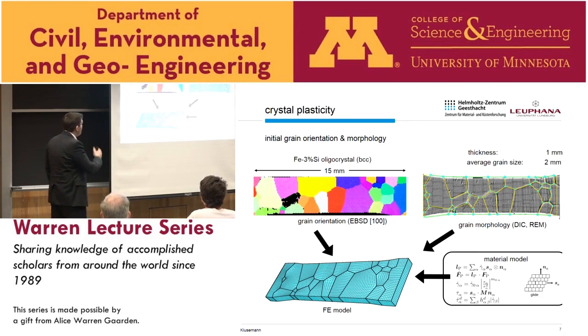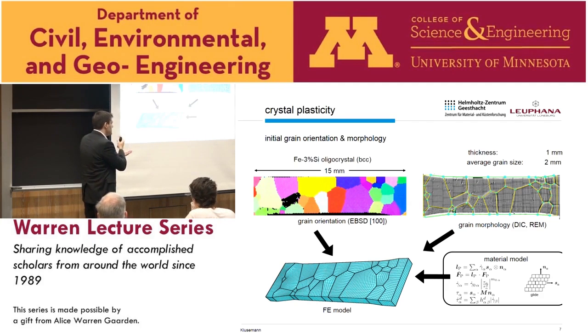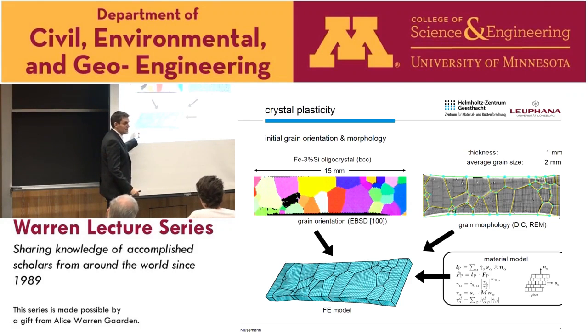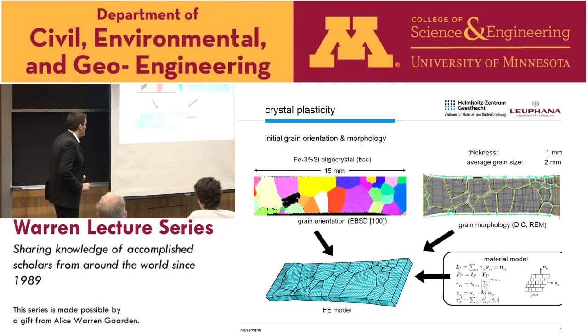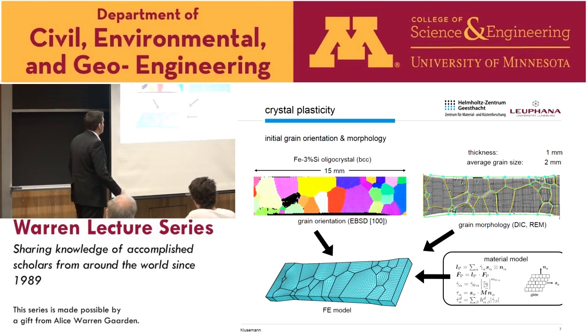these kind of samples. And from experiment we obtained then first of all the grain orientation on the basis of EBSD measurements, as well of course as the grain morphology, where we approximated the surfaces, in particular in thickness direction, to be orthogonal to the surface actually. So this results then in this finite element model, and the real sample looked exactly like this. Now of course the approximation that it is normal to the surface was an approximation, but it fitted quite well to the experimental results.